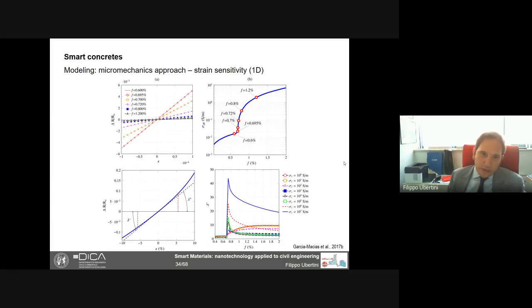But as said, this model can also predict the piezoresistive properties. So we can predict the relative change in resistance or resistivity as a function of the strain. And we can see that the gauge factor is actually maximum at the percolation threshold, and follows the behavior you see in the bottom right. So there is a big jump in the gauge factor when we are close to the percolation, and then slowly it decreases again with increasing amount of nano inclusion. So it's very important to stay at the percolation, and if I may say, to stay a little bit over percolation, to have a material that is more robust with respect to not perfect distributions of the nanotubes in the matrix.